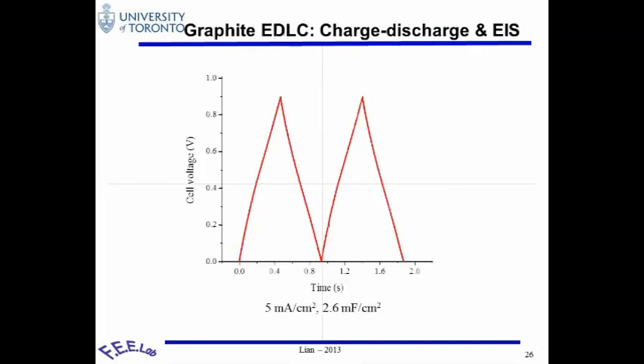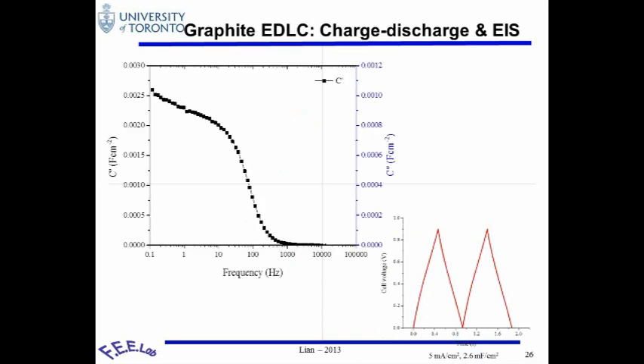A very nice triangle symmetrical behavior shows that it is very capacitive. We also look at impedance, using an approach proposed by Patrice Simon's group, by deconvoluting the capacitance into real versus imaginary. The real capacitance is shown here at the very low frequency, upper left in your case, which should correspond to the capacitance from the CD that we just saw.